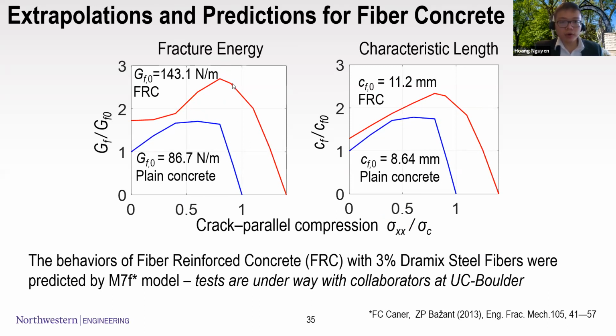So knowing the result for the concrete, we are attempting to do some prediction for the fiber reinforced concrete. And for fiber reinforced concrete, as we know, it has a higher baseline fracture energy. So when you apply the sigma, when the concrete has a fiber, it has a bridging effect that resists the crack opening and leads to the higher fracture energy. However, the trend is kind of similar. And another note is that it has a more gradual drop when the sigma xx comes close to the sigma c.